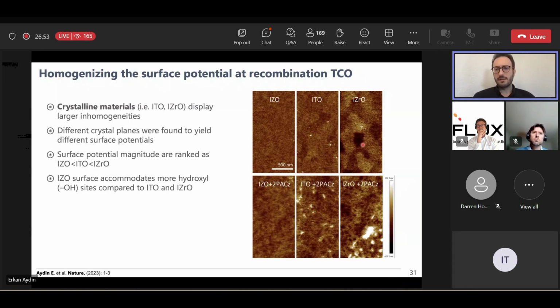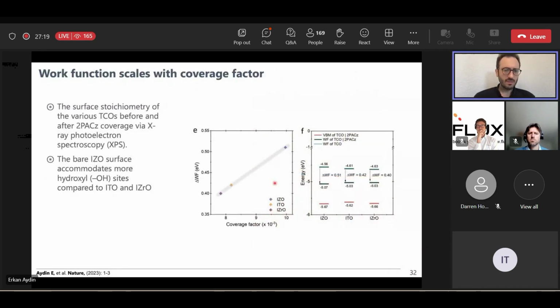And in this case, our strategy was using the amorphous layer. And then we said, why don't we use indium zinc oxide, because there is no crystal here. And we found that the surface potential starts to be more homogeneous when we start using IZO, even after anchoring the SAM monolayer on top of the IZO. So basically, at the recombination junction, we had a chance to minimize the inhomogeneities. And by doing so, we also achieved better coverage of the SAMs, and this also reflected in the work function shifts. And basically, this enabled us more homogeneous coverage of the SAMs at the recombination junction.